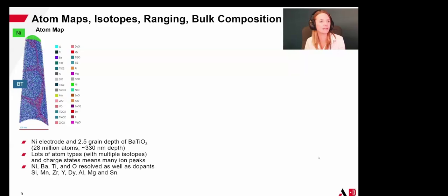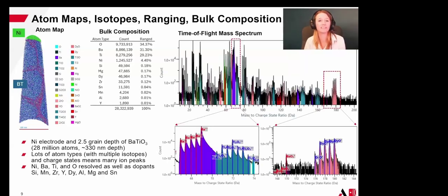Now, if we look at the mass spectrum from these devices, we see that it's relatively complex, which makes atom probe fun. We have our major elements of barium and titanium oxide, plenty of oxide species as you might expect, but we also have a large amount of different types of dopants and minor species. So for example, we have clearly presence of dysprosium oxide confirmed by the isotopic signature, but we can also see things like tin, zirconium, yttrium, and manganese, all as dopants which are modifying those properties.